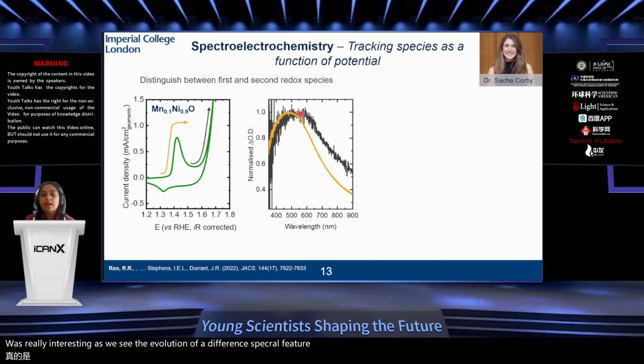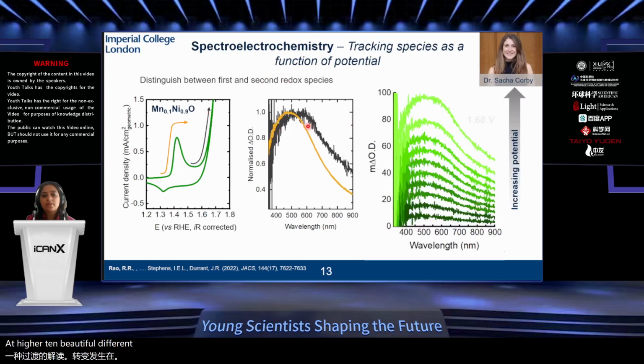And what this in fact suggests is that there's possibly a different redox transition happening at higher potentials. Two different spectral features evolve as you apply a positive bias.